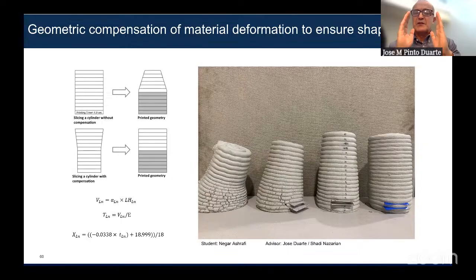So you need to develop an algorithm that counteracts the effect of the deformation. If you want to print a cylinder, you actually use the algorithm to deform the design shape so that you have an inverted truncated cone. So when it gets printed, it's going to deform and get the right shape. That's exactly what this slide is showing. On the left-hand side, you see a cylinder without any kind of compensation, so it will actually lead to collapse, to plastic collapse. And then you see different types of compensation strategies, different types of algorithms.